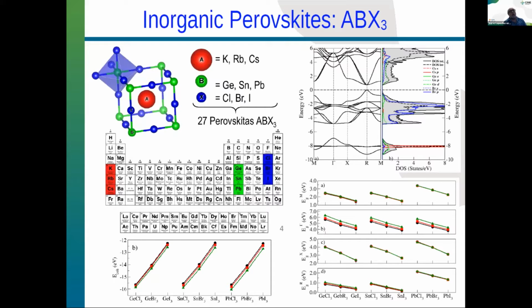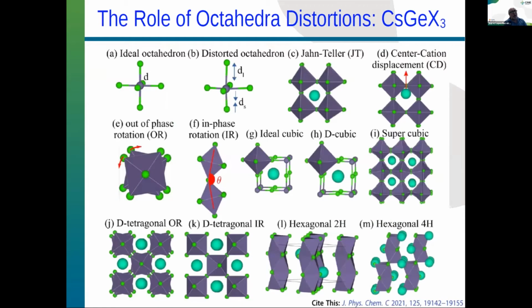It means the following. The cation really is not playing the determinant role to drive the change in the band structure. However, in the case of smaller changes, like 0.1, they are important. But the largest changes come from those species. And then, of course, this was done based on the ideal cubic structure. However, we realized later on that distortions in the structure play a very important role.